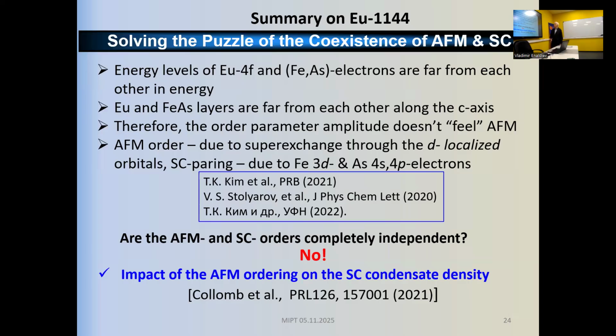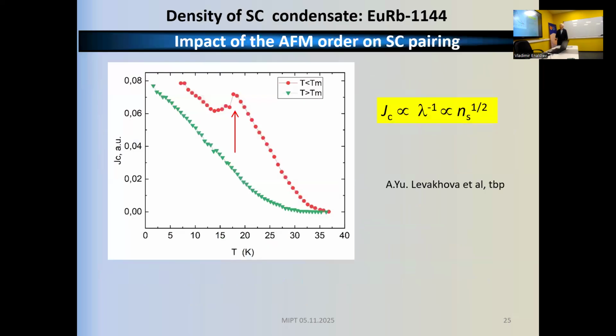At this moment, it may be asked whether the antiferromagnetic order and superconductivity are, for a number of reasons, completely independent. But in fact, they are not, and we have some evidence for this. We are doing measurements. This picture shows the density of superconducting condensate, n_s, which is related to the magnetic penetration depth and the critical current and critical field. The first critical field exhibits indeed some hump in the vicinity of the magnetic transition, so the magnetic ordering does not affect the superconducting gap, but does affect the density of condensate. These measurements are in progress, not published.